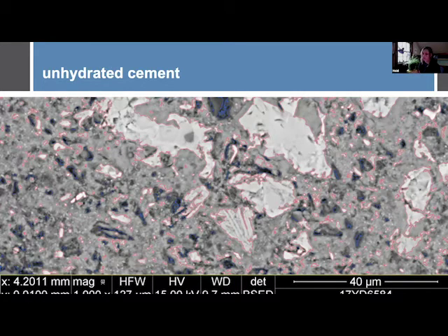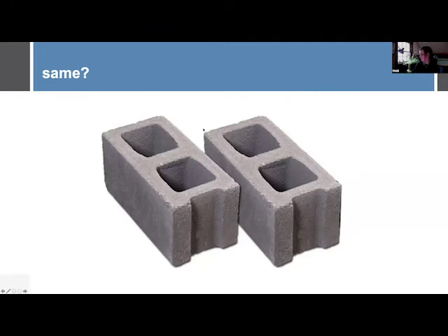And these clusters of unhydrated cement form a hard shield around them so that carbon dioxide will never get to them. So one of the things that this technology does, and the main reason that it works, is that it liberates these little clusters during manufacturing, and it leaves them available to carbonate. So this allows us to utilize that unhydrated cement. And this is one of the things that can bring us back to that 45% potential, which was kind of like the top amount that we could potentially sequester. And also, because of this, less cement can be used.